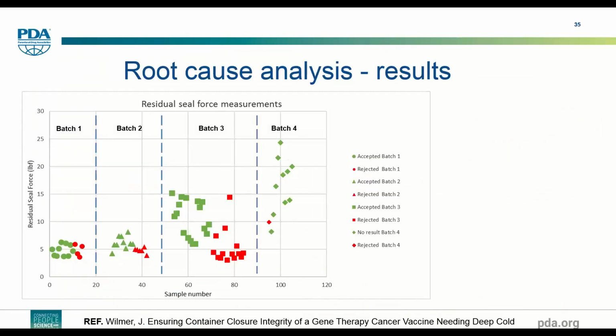Finally, one last RSF CCI correlation graph, and this has, again, a slightly different story. This data was generated on real GMP product. You can see a reference there from, this was presented last year at a packaging conference in Venice. And the story here, you had 4 different batches of GMP product, and the capping and crimping process was actually changed between the first 3 batches and the final batch, batch 4. And indeed, you see in the RSF values that are plotted here, batch 4 samples having, on average, higher RSF values, meaning that they were more tightly sealed by the production process. The first 3 batches had lower RSF values and correspondingly more CCI issues.